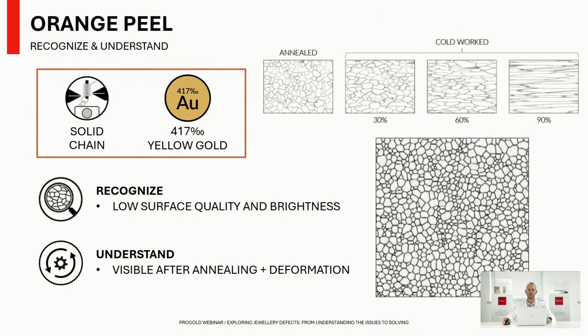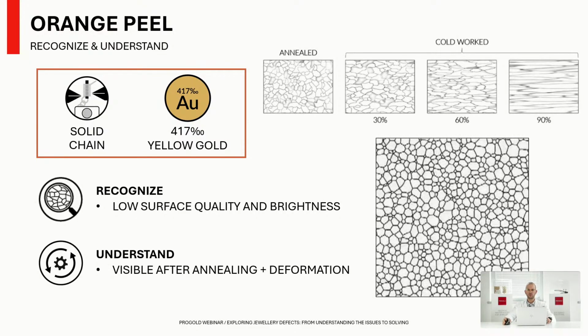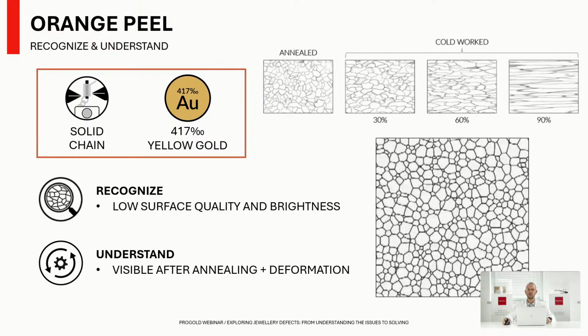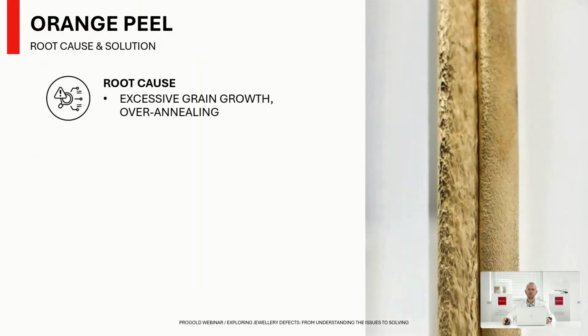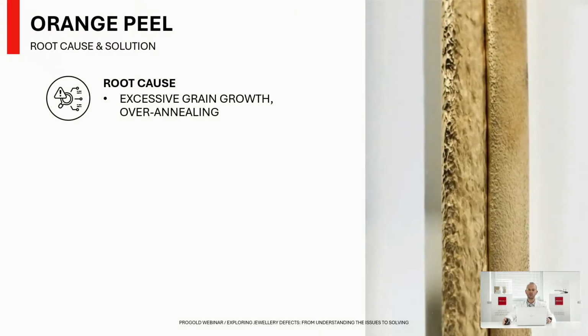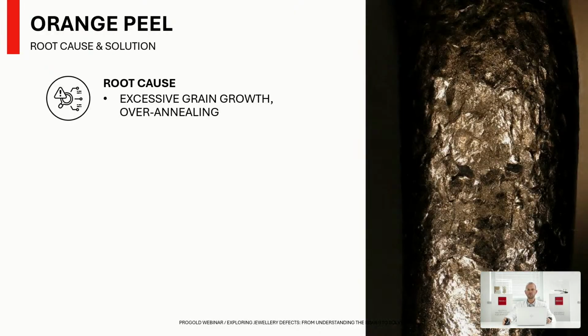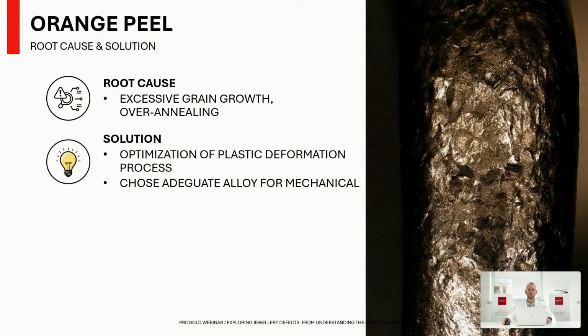This phenomenon appears during the production process of annealing and deformation, and the main cause is over annealing and the excessive grain growth during the production process. How to avoid it? The solution is the optimization of the plastic deformation process, and here the technical consultancy could help you to solve this kind of problem, because knowing the behavior of the material is the first step in order to not have this kind of imperfection.